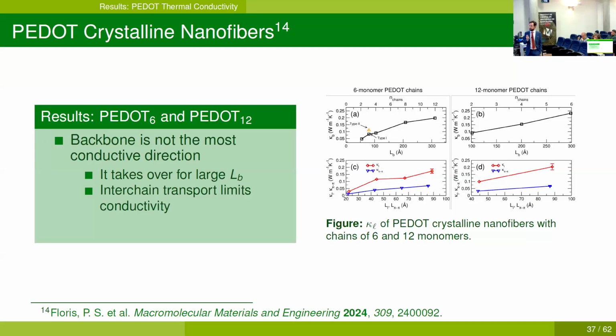And so the first thing to say is that the backbone conductivity is not the most conductive direction. In fact, we have here 0.2 watts per meter Kelvin, which is very similar to the lamellar value.